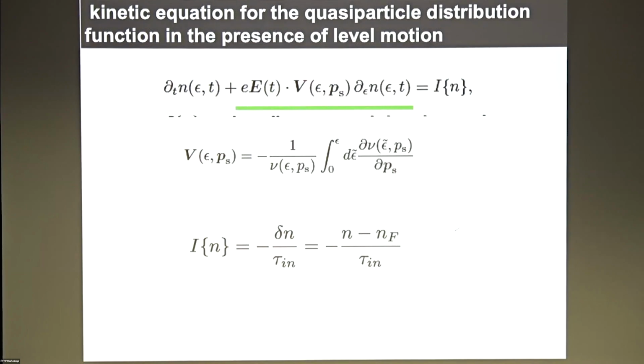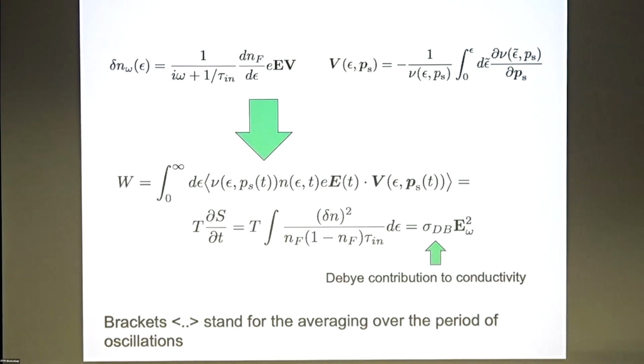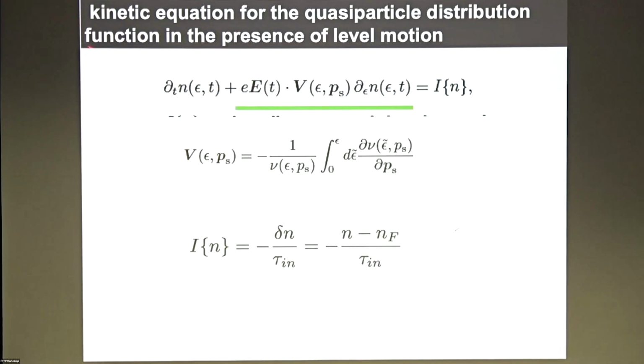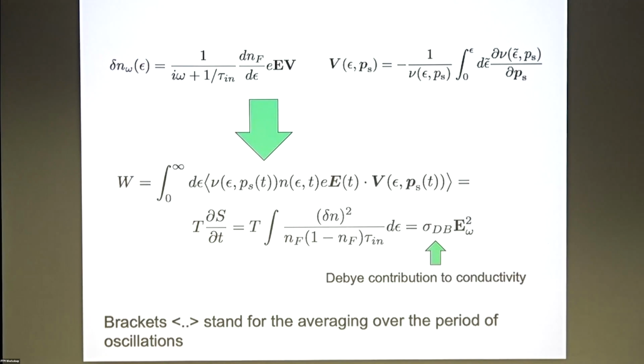And I will speak mostly about the situation when the scattering integral can be written in the relaxation time approximation. I can be more sophisticated than this, but it doesn't really matter. Then I linearize this equation. If I'm interested in the linear response to the electric field, I linearize this equation. This is delta n, proportional to the electric field. This V is the sensitivity, which I mentioned. Substitute this expression into the expression for the entropy production rate.